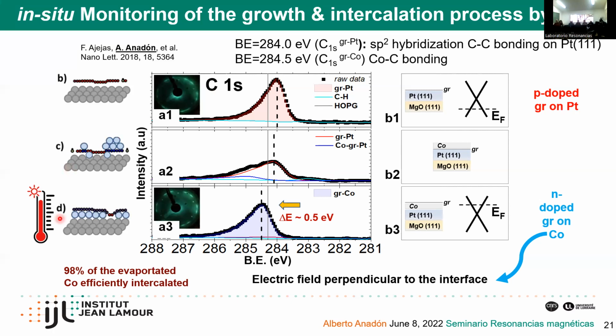So we have a combination of two different peaks in the C1s of carbon. Then when we heat, the cobalt goes below the graphene, and the first peak that we have is completely shifted to the left. So we have a very efficient intercalation of almost 100% of the cobalt in the system. And now, as you can see, the peak of carbon is shifted to the left. So now graphene is n-doped. So we are creating an effective electric field perpendicular to the interface. And this is very important because it's what happens in Rashba interfaces.